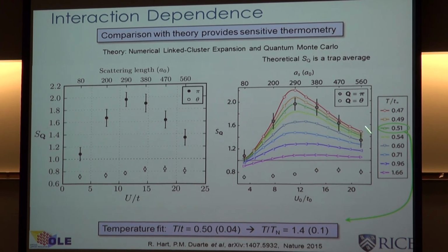And by the way, this is averaged over the inhomogeneous distribution. And so this U naught over T naught refers to the center of the cloud. So anyway, that fits to something like 0.5 of T over T of 0.5 with about a 10% uncertainty. And so that's about 40% above the Néel temperature. So even though it's above the transition temperature, there's short-range order that begins to develop before the Néel phase is fully, until you get into the temperature low enough to see the Néel phase, you can still see some magnetic order. And even at relatively high temperatures, you can still see a little bit of that effect.